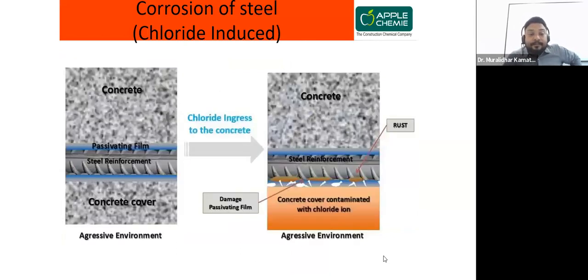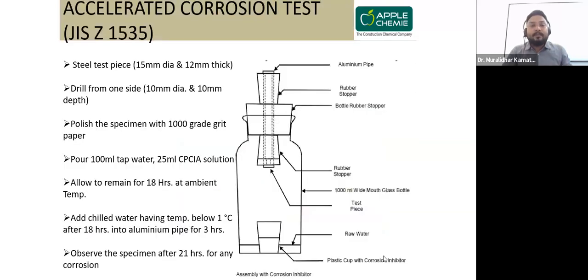Again, what the corrosion inhibitor is doing over there: see over here, this is the concrete surface, there will be a passivating film. So this passivating film, when you are going to add the corrosion inhibitor solution, the pH level of that concrete surface is going to be maintained at basic. It will not come down. Whenever the pH comes from 13 to 8 or 9 side, at that time corrosion initiation will start. Without that, it cannot damage your reinforcement. So the corrosion inhibitor solution will do that. It will not allow your concrete pH level to reduce. And this can be tested.